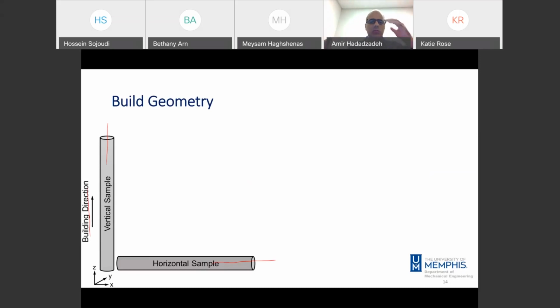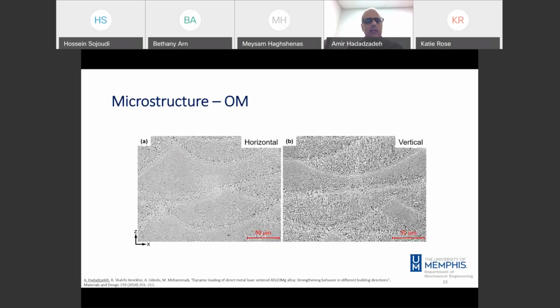characterization, and any metallic material that you start to characterize, you start most probably with optical microscopy. So I did the same thing, and from optical microscopy we can just see a general structure of the material. This is the side view. So the z-axis shows the building direction. We are looking at both samples from the side view. We can see the overlapping melt pools. These are the melt pool boundaries, for example here. And this type of structure is called fish scale structure, because we can see kind of fish scale from the side view.